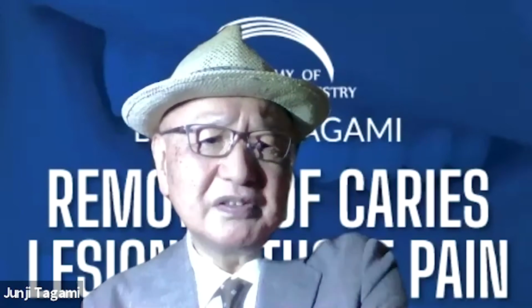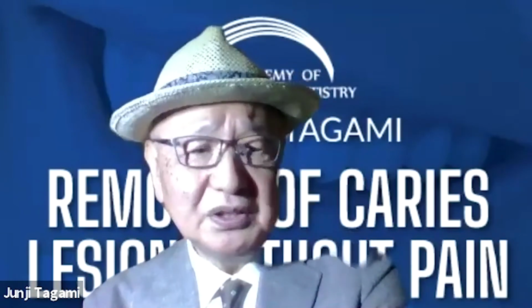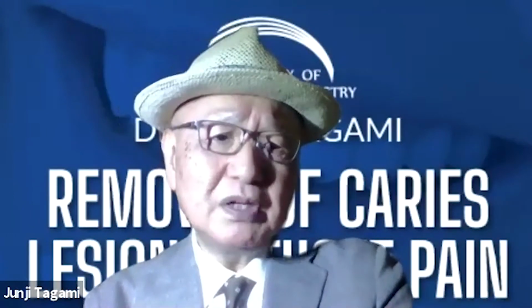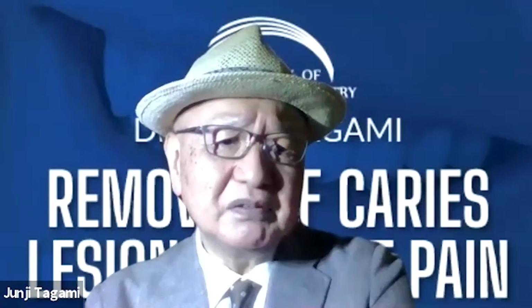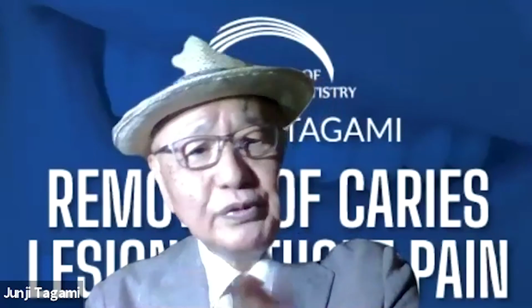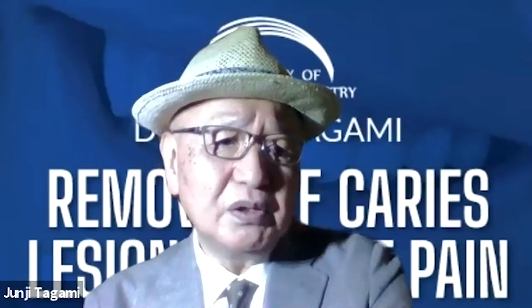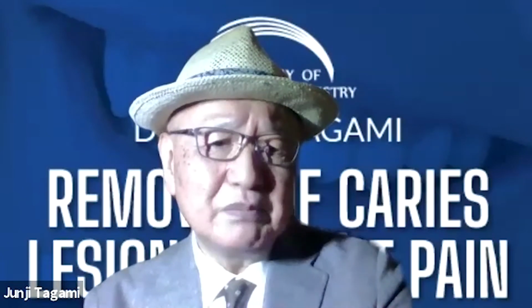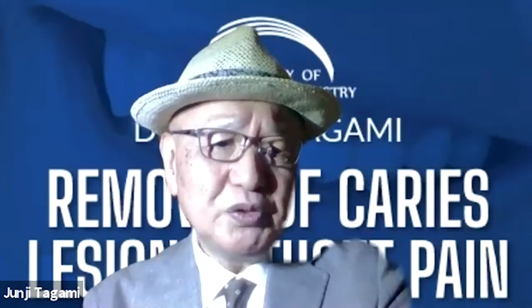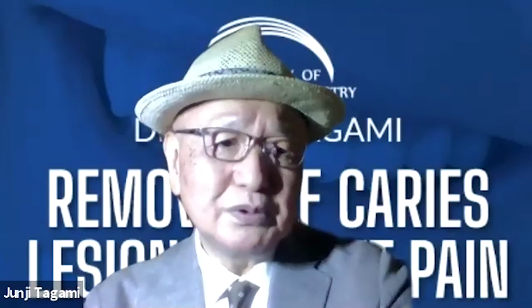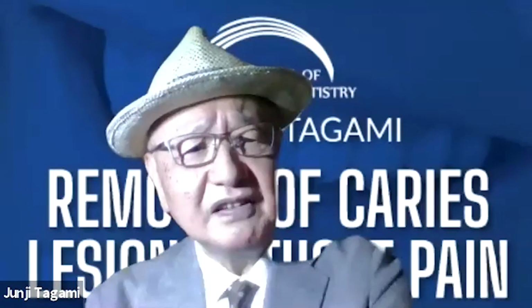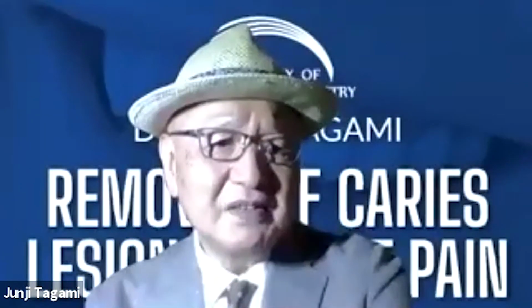The filler particle tended to become much smaller than before, and we can continue to use the same flowable composite as an incremental filling technique. And finally, we can complete the whole restoration with the flowable composite only. This kind of flowable composite restoration is not from the bulk fill flowable. We use the so-called restorative flowable composite as the whole restoration, including the posterior composite. And this restoration is now widely accepted among Japanese clinicians.